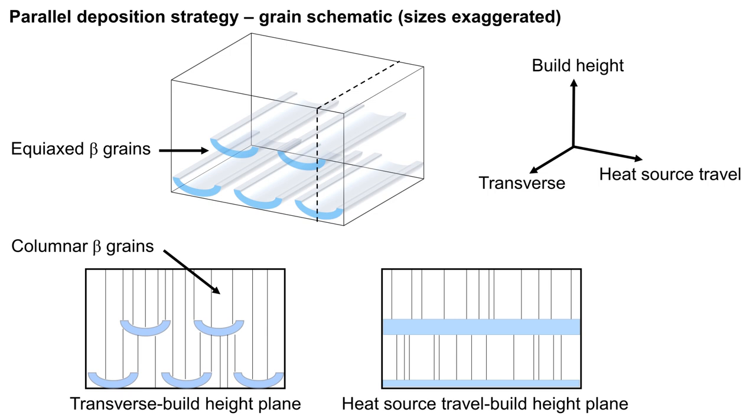On top of the heterogeneous nature of the beta grain structure, one's view of the structure can be biased by taking particular cross-sections, as shown on the right here. However, overall, the beta grain structure was refined enough in the X-beam Ti64 material to produce a weak texture, and much more isotropic mechanical properties would be expected compared to a fully columnar beta grain structure.